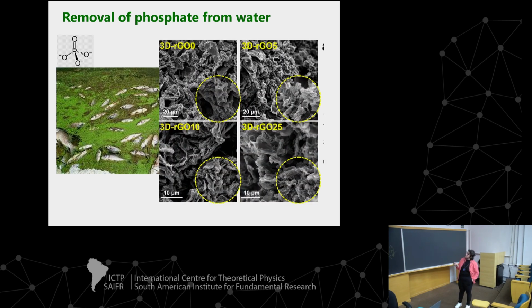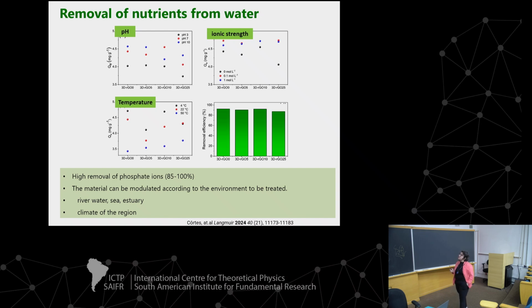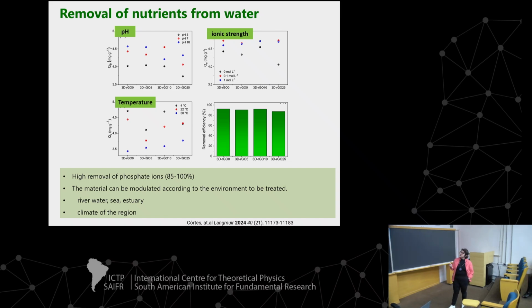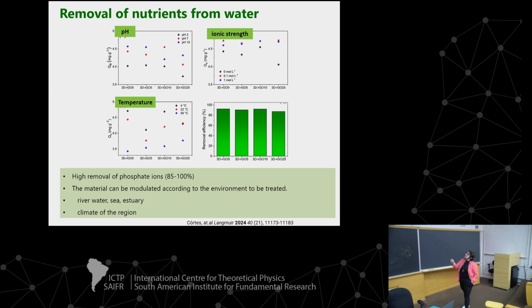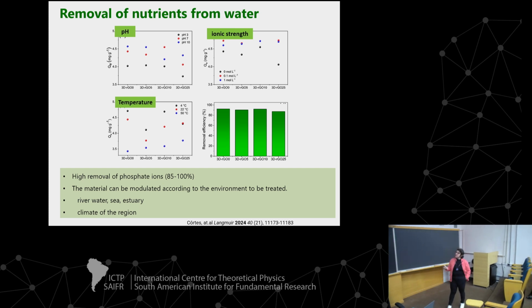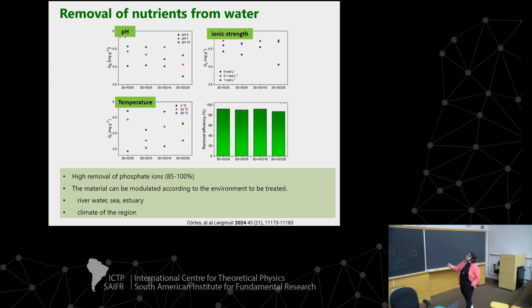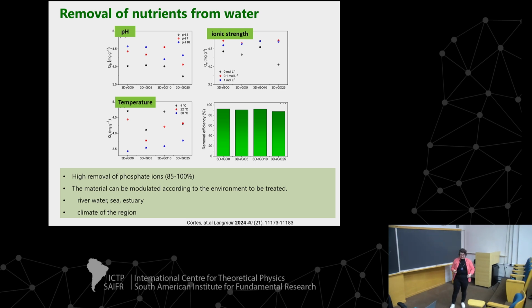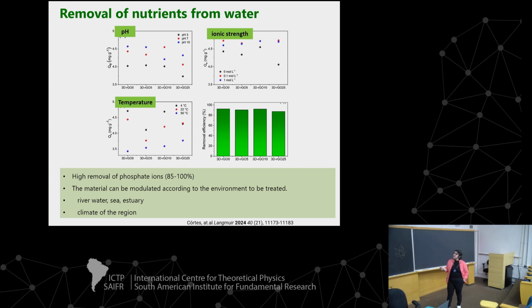We tested these different materials, more oxidized and more reduced, to remove this phosphate. We tested different mediums, changing the pH from acidic to basic, and the ionic strength, from a low ionic strength mimicking a river environment to a high ionic strength like a sea environment, and changing the temperature from a cold place to a higher temperature like a tropical environment. We show that depending on these parameters, we can remove more or less phosphate, but always removing more than 85%. It's a high amount of phosphate removal.